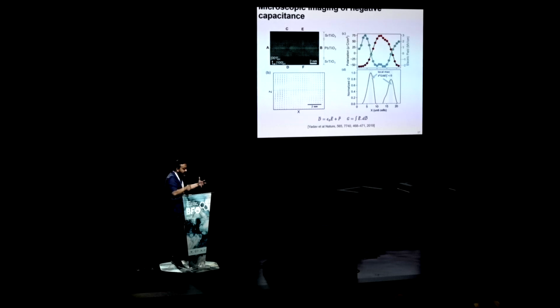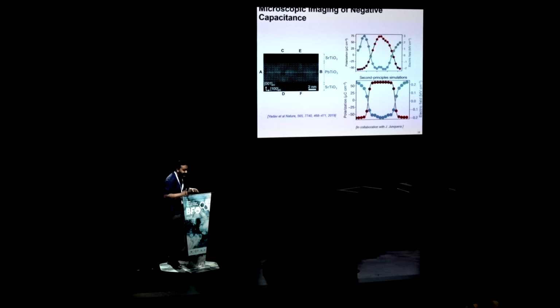So we, in fact, could both image and calculate a negative capacitance in the material and then measure macroscopically the capacitance enhancement. And this is work that was also done in collaboration with Javier, who did fantastic second principles calculations, and very, very rigorous. He spent some time at Berkeley as well.